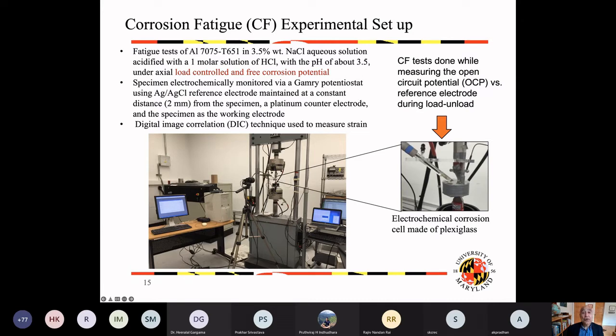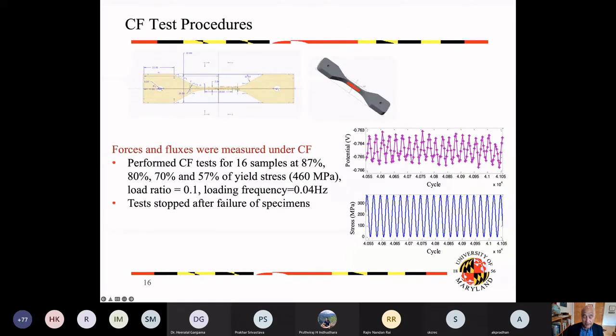Corrosion occurs because the material is aluminum, which is used in aircraft structures, and we are corroding it with 3.5% sodium chloride. And here is the specimen that is being corroded. Here is the area that actually causes the damage. And then there are 16 samples that we tested. This shows the corrosion results. It shows the potential and cycle.